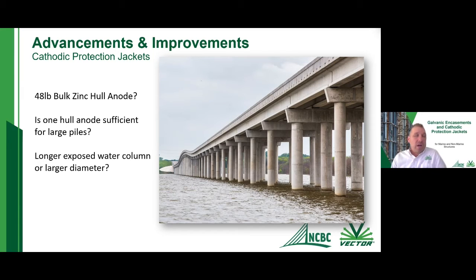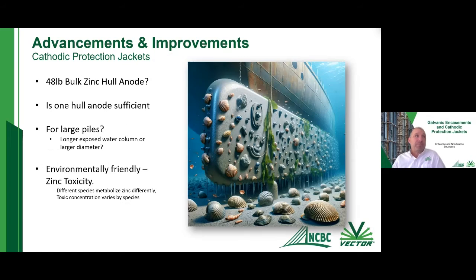Another thing is that typically, in the past, one hull anode was used for every type of pile out there. Whether it was a 14-inch square pre-stressed pile, all the way up to very large drill shaft piles that are 60 inches in diameter, one zinc hull anode was used. And what about your water column? The depth of the piles: do you only have 10 feet down below to the mud line, or do you have 40 feet? The more exposed pile you have in that water column, the more cathodic protection is going to be required to protect that area as well.